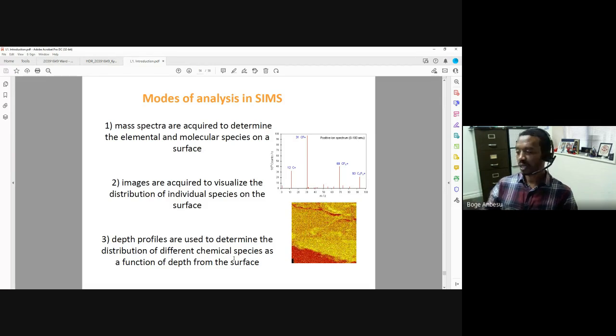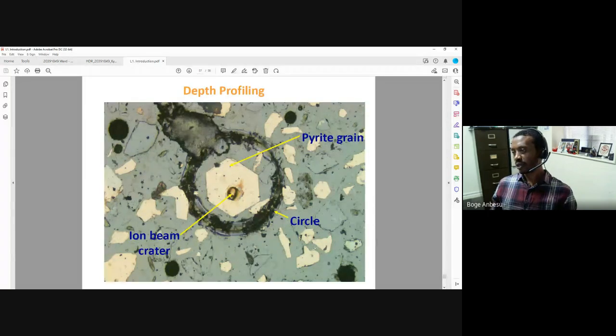But with a SIMS analysis, you can also map those fragments coming from the sample and get something like a more visual observation of the distribution of each element on the sample. And sometimes if you're interested, you can even go a bit deeper, maybe a few nanometers deeper into the sample, and see how the concentration of a particular element, if it's gold, varies as you go deeper and deeper into the sample as well. But this is probably a few nanometers deep. So this may be what you're getting at.